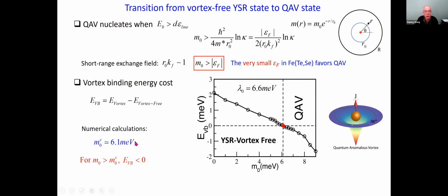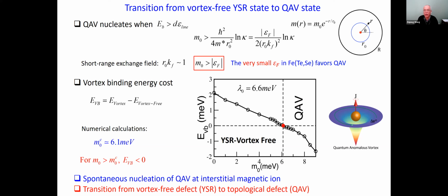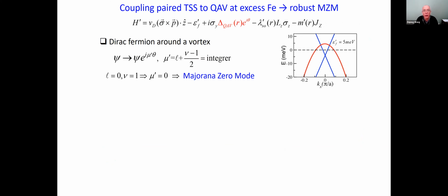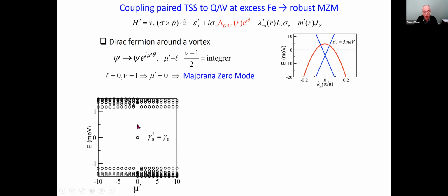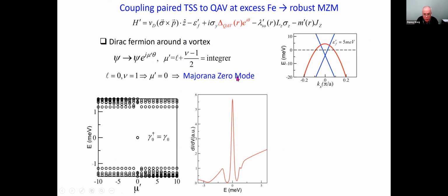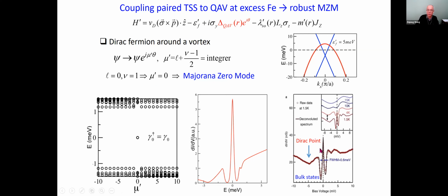And this is a complete numerical calculation. Here we plot this binding energy as a function of the exchange field. On this side, you have the Yu-Shiba-Rusinov vortex-free states. But when the exchange coupling becomes stronger, larger than the Fermi energy, you have a quantum anomalous vortex spontaneous nucleation. In fact, there is a transition now going from Yu-Shiba-Rusinov states to a vortex state. Okay, and now once we have the vortex, of course, we just couple that to the superconducting topological surface state. That is the blue line. Now you got the extra Berry phase. You get integer quantized core states with the zero mode. But for this set of parameters, the core states are cleared out from the vortex core, and that gives rise to this very robust zero energy peak, and that compares very well to Shuhan's experiment.